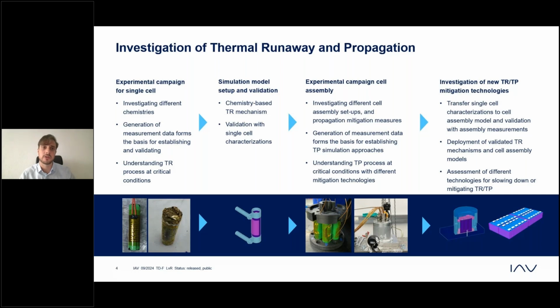The next level was, because we are also super interested in the thermal propagation, to do similar experiments, but not only with one cell, but in a module with more than one cell. So we put 7 cells together in a module where the central cell was penetrated with a nail, and that one then saw thermal runaway, and we would see if the neighboring cells would go into the runaway as well.